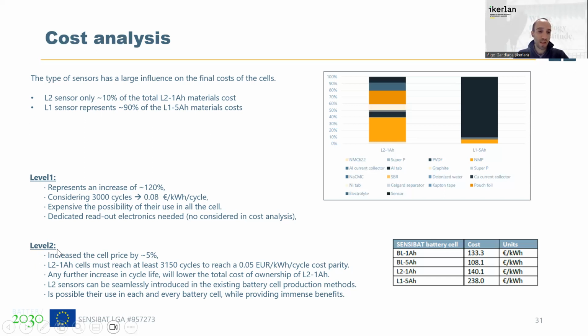On the contrary, the level 2 sensor represents only an increase of the cell price by 5%. Considering that a baseline cell reaches 3,000 cycles, to have cost parity per kilowatt hour cycle, we need to reach 150 more cycles when we are using this new sensor. And as we have more information about the cell, we think that this is possible. And if we can increase the cycle life of the cell more using this sensor, we will lower more the total cost of ownership of these L2 1 ampere hour cells.